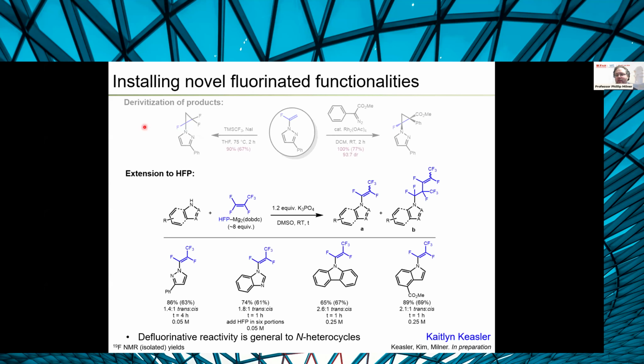And one thing I just want to note about the advantage of this approach compared to just using gas-loaded cylinders is Caitlin found hexafluoropropene is particularly electrophilic, and you can get polymerization or oligomerization here. But she found that, for example, you can solve it in some cases by adding the gas-loaded MOF slowly to the reaction in a couple of portions, which is not something that would be very easy to do with the gas itself. And so we think this is really enabling us to find new reactivity that would be hard to identify using, say, balloons filled with gas.